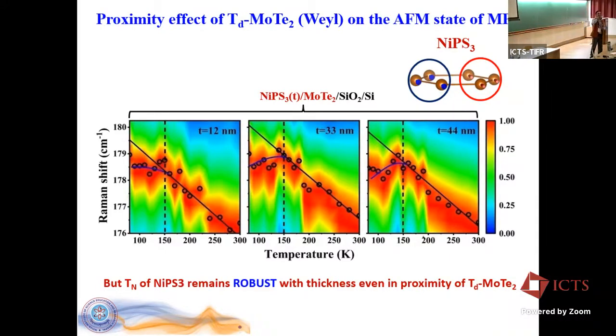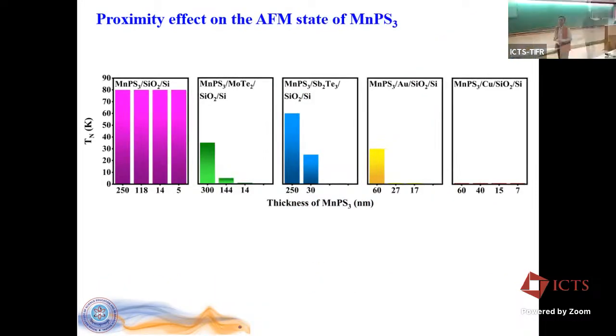So that's where Shubhro was very helpful. So we figured out many different ways, and we explored different experiments now, not just with MoTe2, but with other topological systems, for example, Sb2Te3. Then we tried with a thin layer of gold below MnPS3 and a thin layer of copper below MnPS3. Why? Okay, MoTe2 is a Weyl semi-metal which has a strong SOC and has surface states. Okay, these two are the important players which we came up with after the discussion with Shubhro.